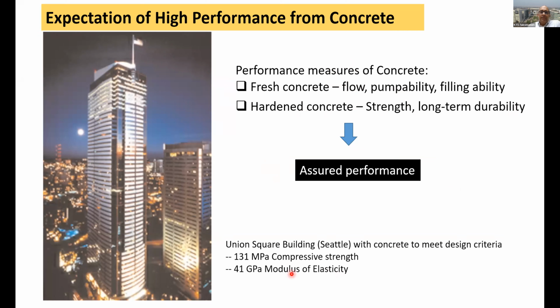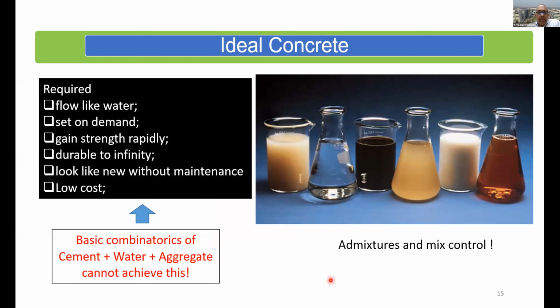Just to give you one example of a performance measure, this is the Union Square building in Seattle, where they've used concrete that is 131 megapascal. So it's a very strong concrete, but the modulus of elasticity of concrete was also specified. They expected concrete to have a minimum 41 GPa modulus of elasticity, required for the stiffness. Because, if you remember, the sway, the deflection of the building depends not on the strength, but on the modulus. So in this particular case, they specified this as a requirement, one of the properties that was specified.